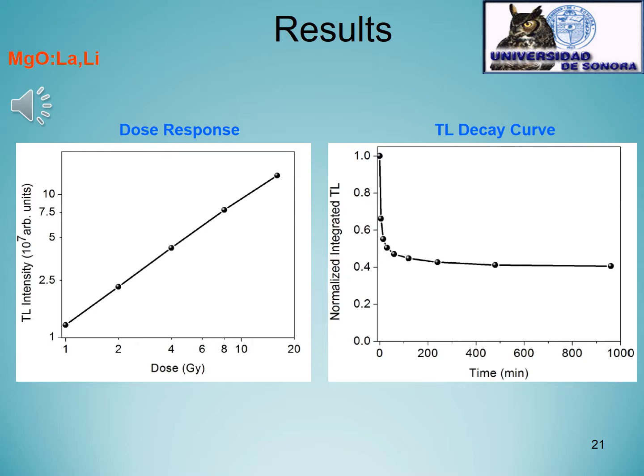Moreover, we can observe very desirable features for TL dosimetry on this material, such as a linear trend of the dose response in the range of doses studied, and also an asymptotic behavior of the TL decay curve, which means we have a very stable signal during the time of storage of electrons. With these two features, we can propose this material as suitable for the dosimetry applications I mentioned before.